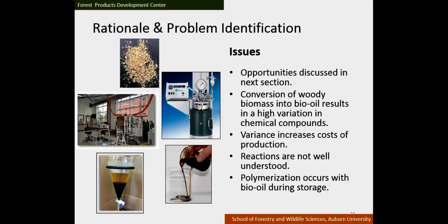So on the left side is his pyrolysis lab, and on the right side is a Parr reactor, where we do the liquefaction. So the liquefaction is where we add a solvent to the wood, and we heat it at high pressure and temperature, and we take out the oxygen, and then we can convert it to a similar looking bio-oil, but chemically it turns into something very different. They look the same, but they can be quite different in their chemistry.